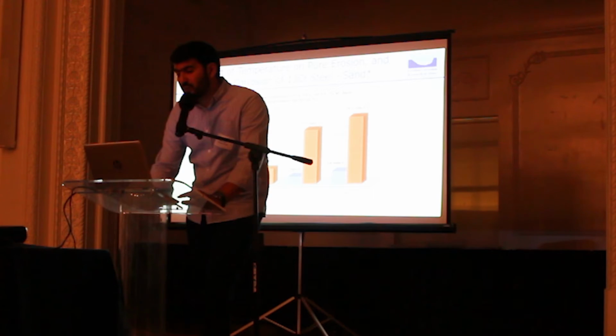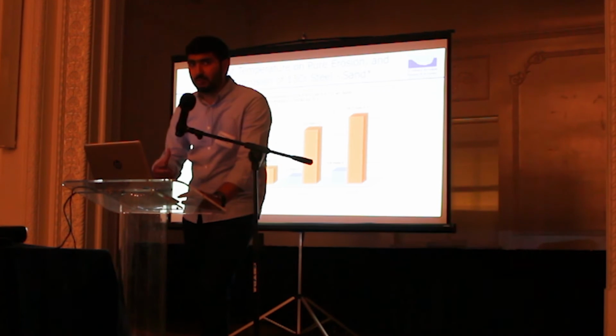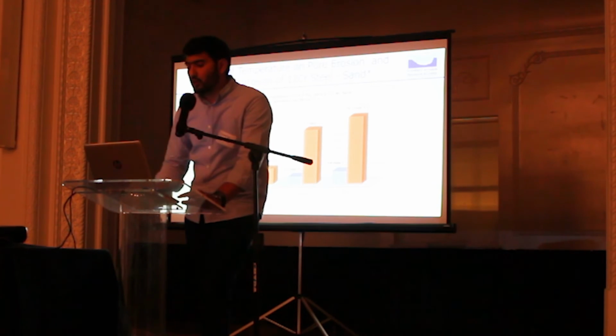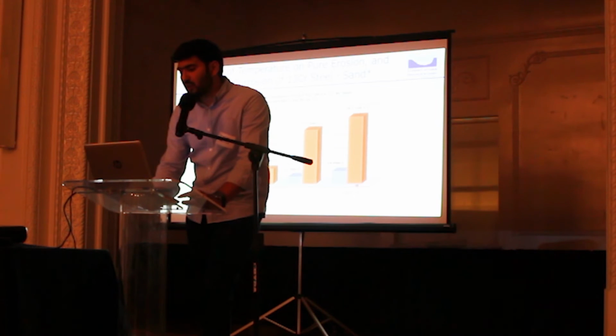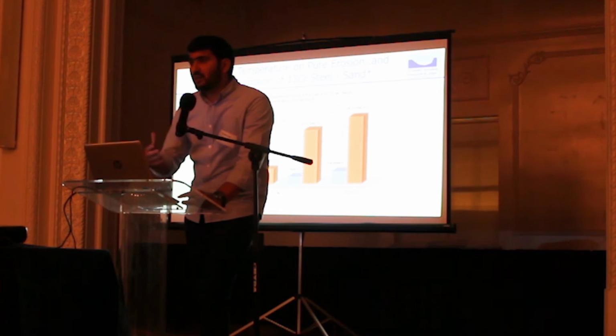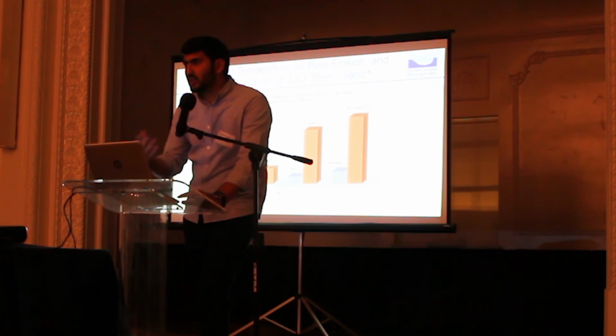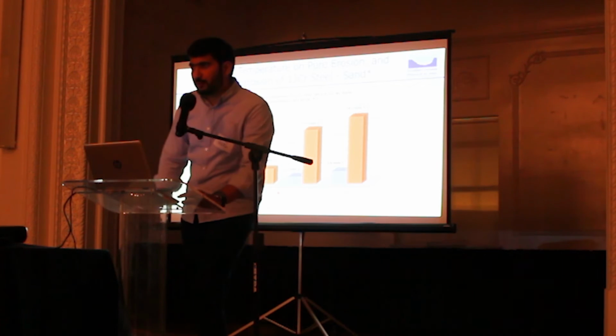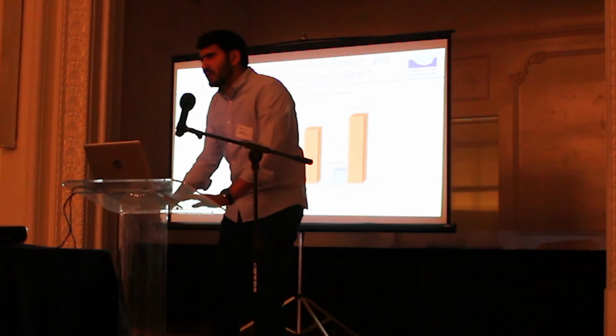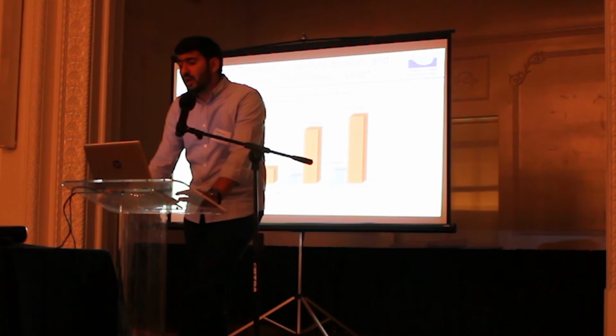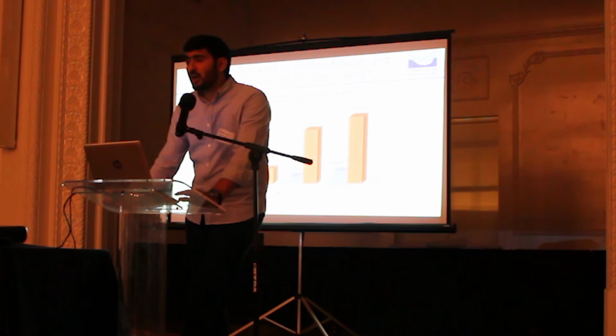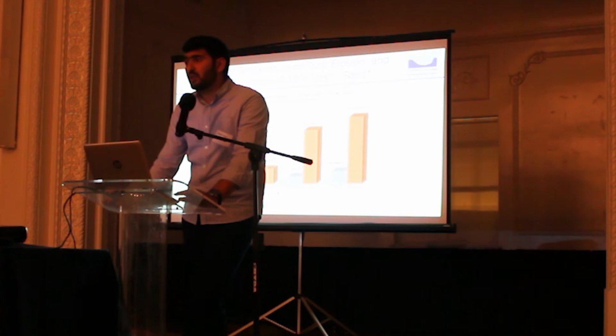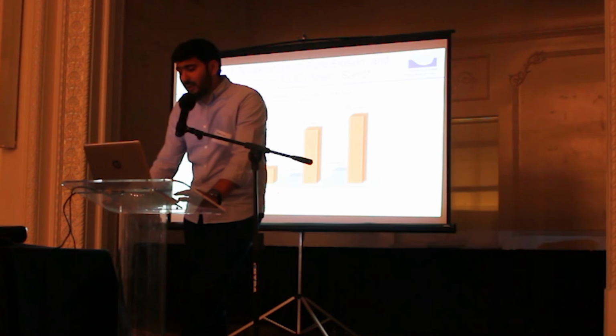As we can see here, there is a difference between pure erosion and erosion corrosion for each of these data, and this difference, or the synergism between erosion and corrosion, is increasing with increasing temperature. And as for future work and work that is still in progress for the performance of CRAs, we are conducting studies on Inconel 718 and also the duplex stainless steel 2507, alloys that are commonly used in the oil and gas industry.